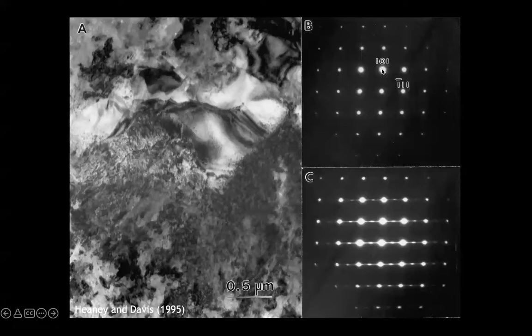And the appearance of these spots is actually the result of the same kind of constructive and destructive interference effects I've been talking about with respect to color, but now we're getting close to the atomic scale. What I really want you to note is the arrangement of spots in this diffraction pattern here. When we compare the primary spots in a diffraction pattern taken from this mottled stuff, it's the same. And so what that tells me is that the crystallographic orientation of all of these thousands and millions of nanocrystals within this mottled region here is identical to the crystallographic orientation of this coarse-grained crystal.